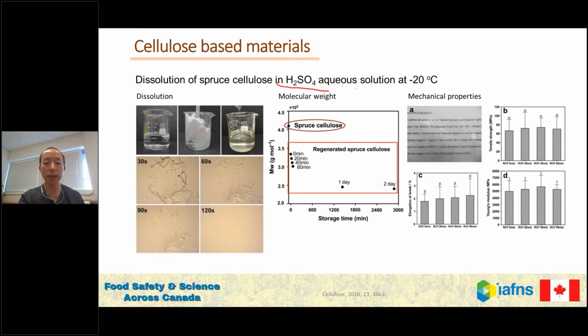Another solvent we can use is sulfuric acid. Again, we just use sulfuric acid and water. What we need is a relatively low temperature. So if we put cellulose in the solution, we can get, again, a transparent solution. Under the microscope, we can see cellulose can be dissolved quickly. With this method, we can also make transparent films, and the property of this film is quite good. It's comparable to commercial products like cellophane. The mechanical properties are comparable.